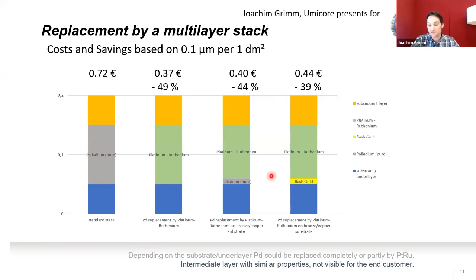Another opportunity, if you don't want to do the palladium, you can do a flash gold as well. And if you calculate at the actual pricing, you get around 39% still in a saving compared to the pure palladium intermediate layer. It's still 39% and comes to 0.44 euros. So this is the way how to have your layer sequence to get these numbers of saving.